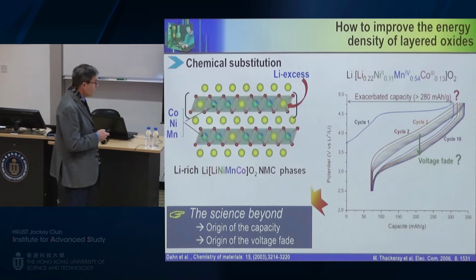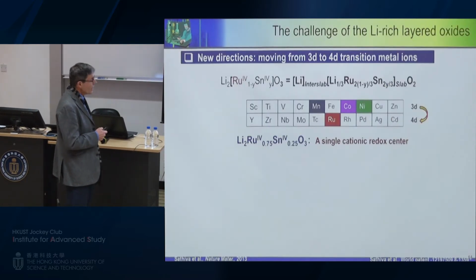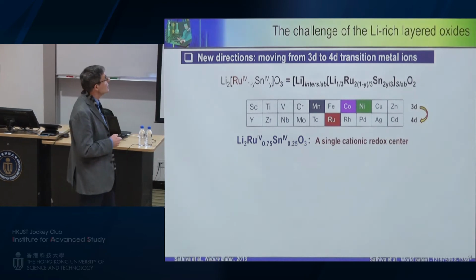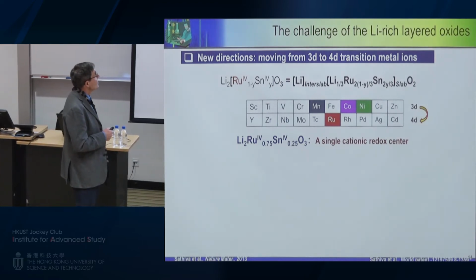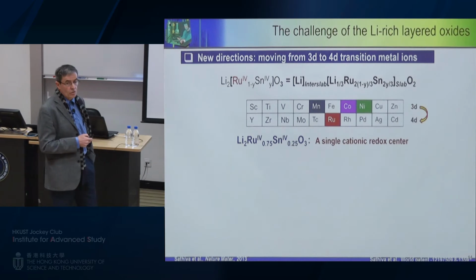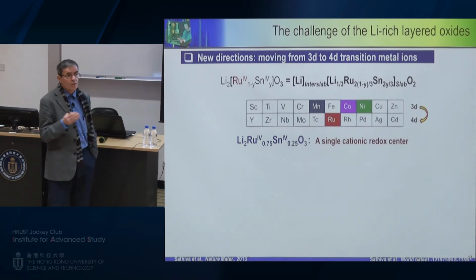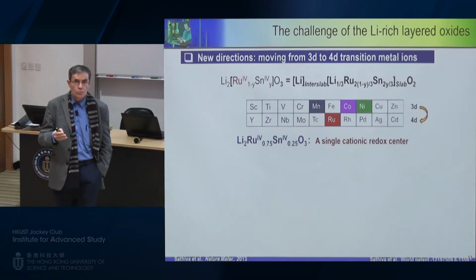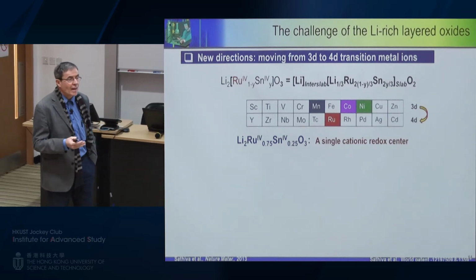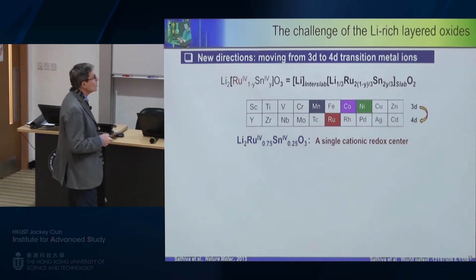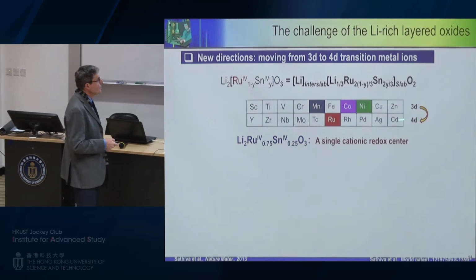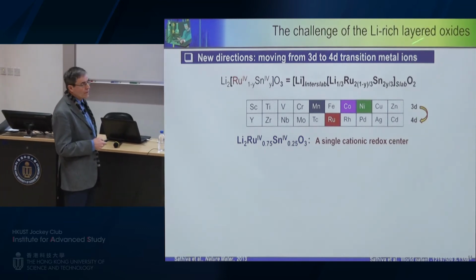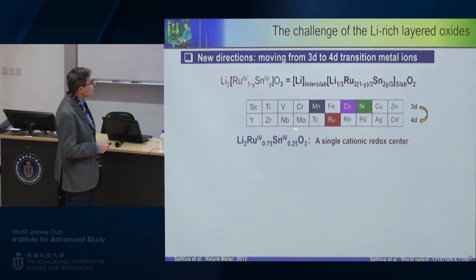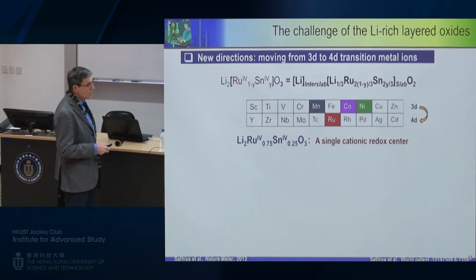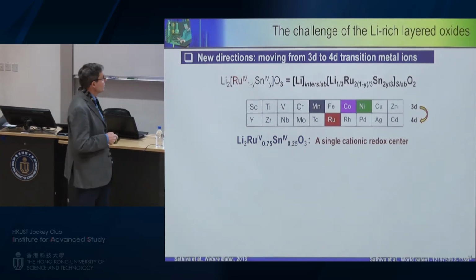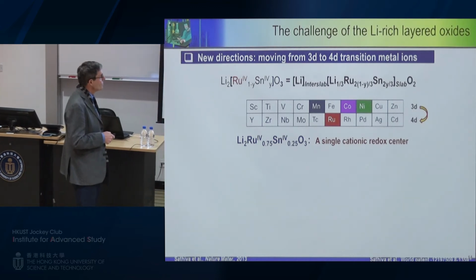So we have been working on this field, and we try to attack the problem differently. Indeed, it's quite difficult because when you work with nickel, cobalt, and manganese, you have three different redox centers, and it's very difficult to control which one is going to be active. So we decided to move to compounds using ruthenium instead of nickel, cobalt, manganese. And we prepared this type of compounds where now we have a single cationic center, which is ruthenium.